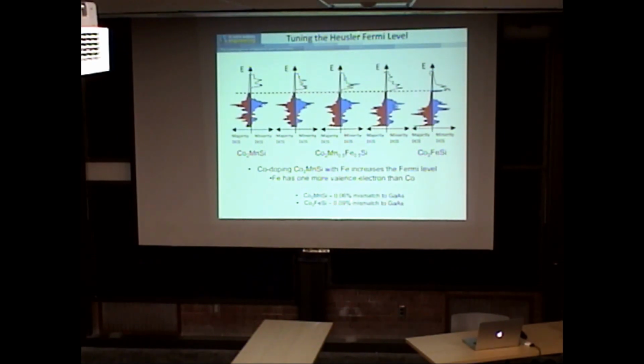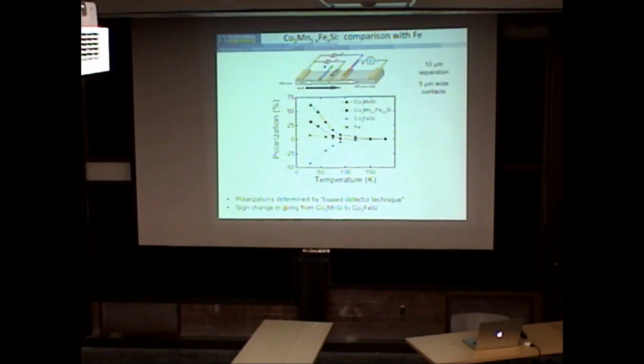The mismatch is 0.09%, so it should still be a good lattice match, and we can grow it. And we've grown them. From these lateral spin valve measurements, you can see here cobalt-2 manganese silicon, modeled with the spin drift diffusion model, gets somewhere around 60 to 70% spin polarization.